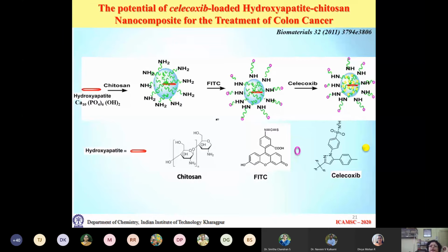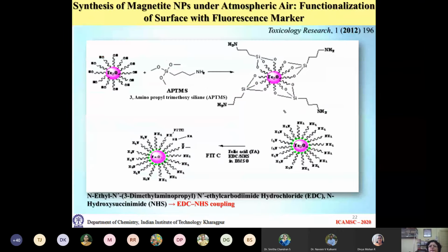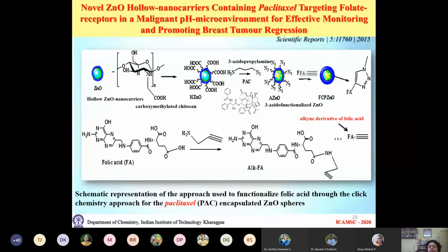It is going to be released by the pH. The moiety is going to be detached at an acidic pH. Whenever you are having a pH triggered release, you necessarily look for a moiety which is going to detach at acidic pH, because all throughout the body fluid the pH is around 7. When you reach the tumor site, the pH suddenly changes to less than 6. So if you have a less than 6 extracellular microenvironment, that means you have reached the tumor site.